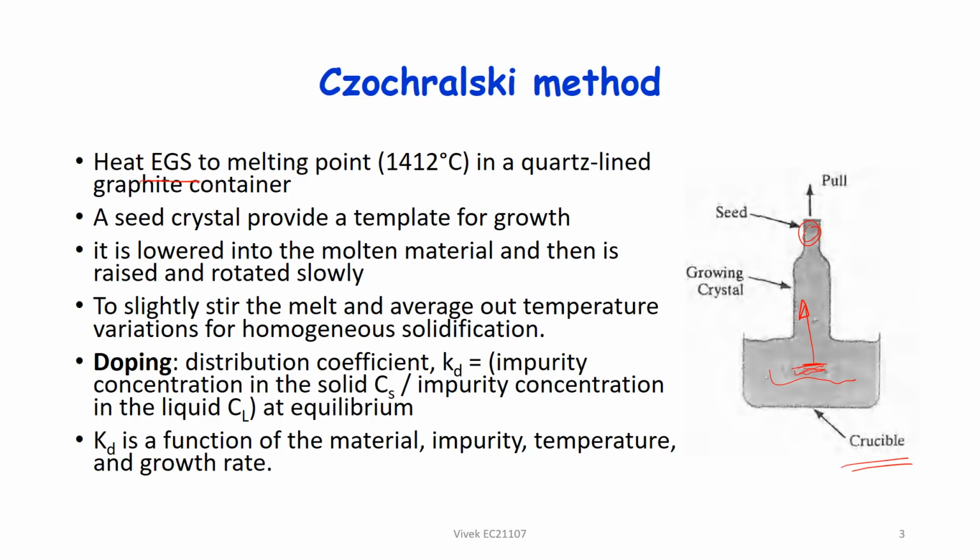Usually it's quite long, quite heavy, bulky. This single crystal basically provides a template, and the liquid silicon attaches to the template and forms the silicon crystal. There is another thing: when it is raised, it is slowly rotated. Rotation has two purposes. It basically stirs the melt, and it averages out the temperature, so that the solution is more homogeneous.